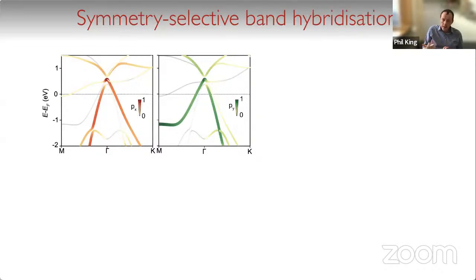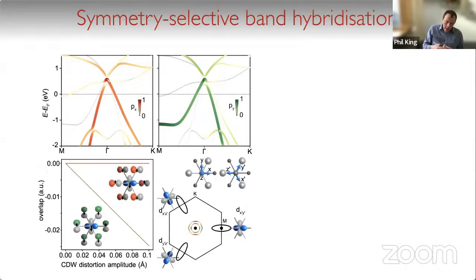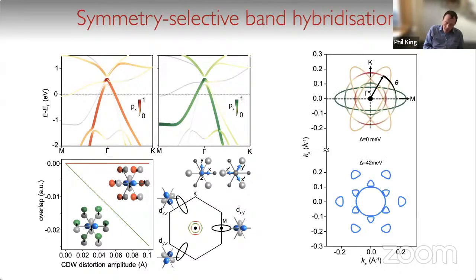Now, just as for the palladium telluride that we were talking about, we have px and py derived sets of states giving us dispersive valence bands in the system. And when you have the periodic lattice distortion that accompanies the charge density wave transition, it turns out that only the py derived states can couple to this periodic lattice distortion, whereas the px derived states can't couple to this, and so won't hybridize.